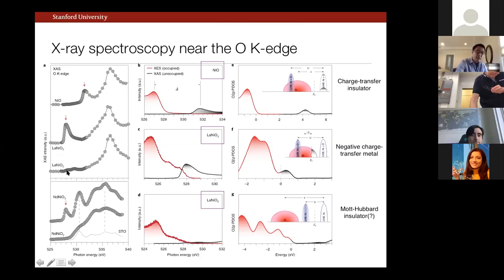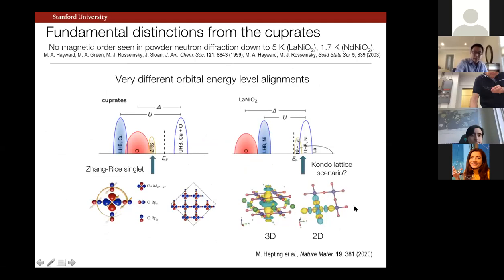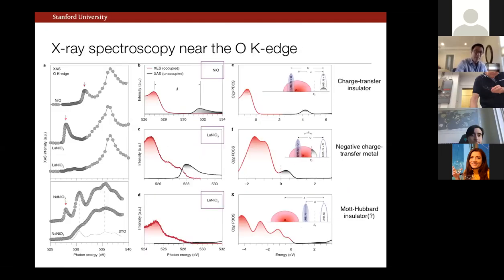And so this, we think, is a measure of this x squared minus y squared state. So it is there, but it's very small amplitude, and that is very different from, again, the cuprates or the other oxidation states of nickelates, okay? And the same can be said for the neodymium version. So this was a study just of the parent compounds.